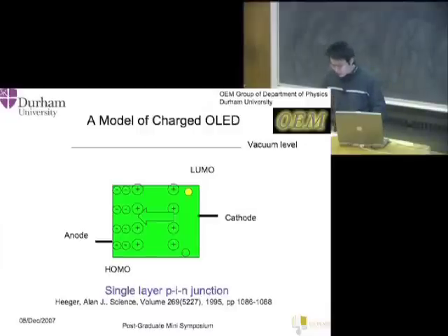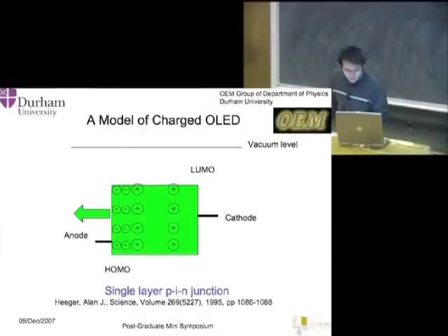And this is very important to increase the efficiency of the OLED, because for most stable metals that can be used as the cathode, for example aluminum or silver, they all have a Fermi level of about 4.2 electron volts. So this causes a pretty big energy gap between the Fermi level of the cathode and the LUMO of the small molecule. For this kind of structure, it can reduce the energy gap. So it's very good.